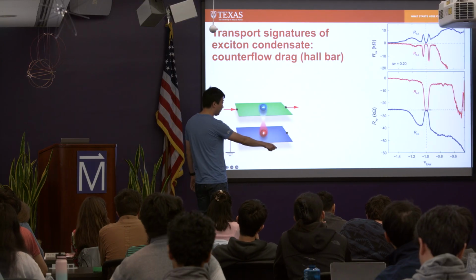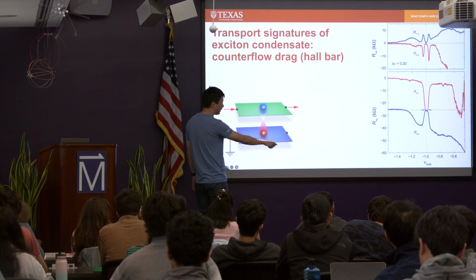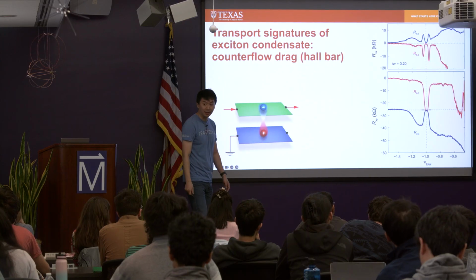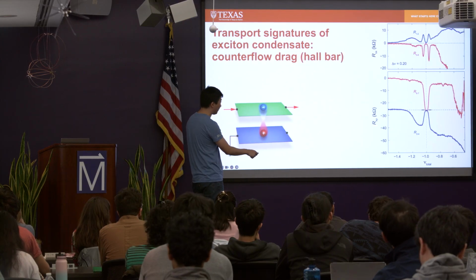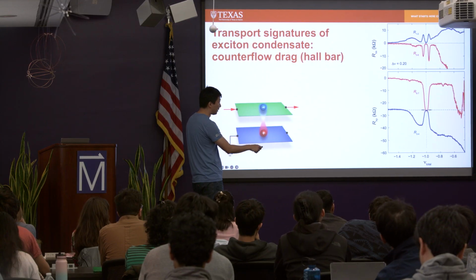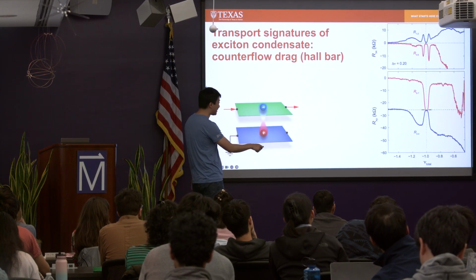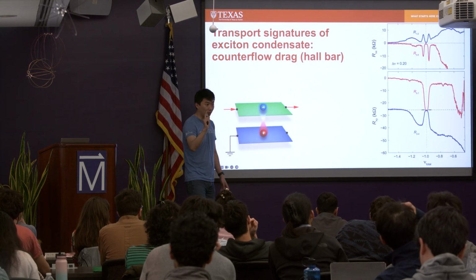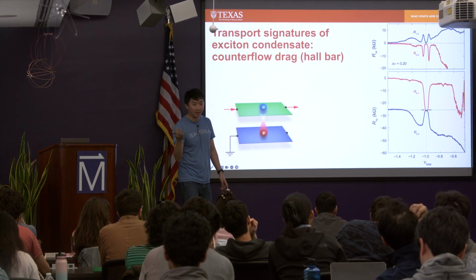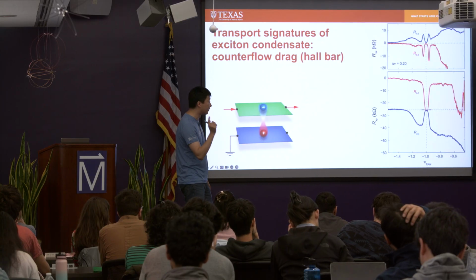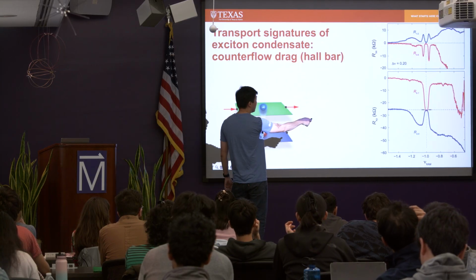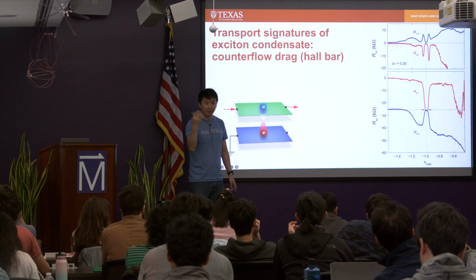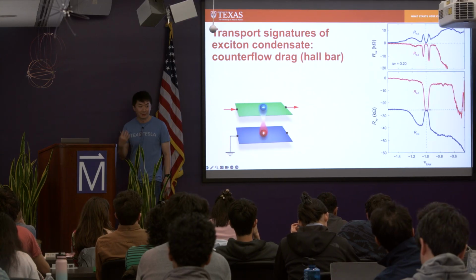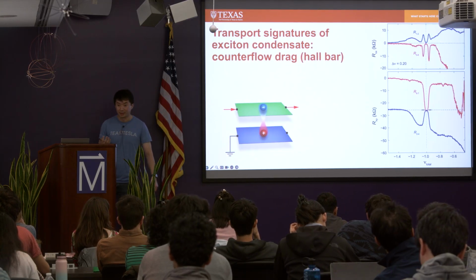Total filling of -1, that's when each layer is at half filling. This is where we expect the exciton condensate to appear. The bottom panel is plotting transverse resistance measured from the active layer and the passive layer, right? And you can see that both layers show a quantization at 1, meaning that there's a single edge channel that shares the two layers at the same time, right? And when current flows along this edge channel, longitudinal resistance drops to 0 for both the passive and active layer, meaning that the exciton is flowing dissipationless, right?